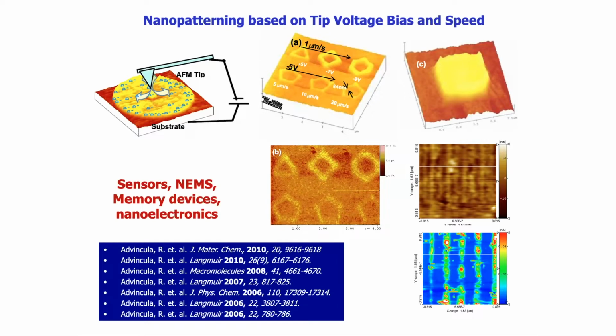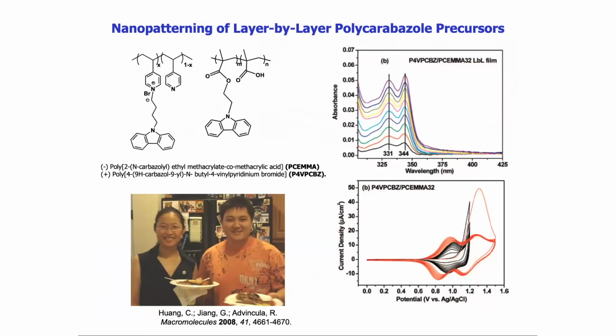Now, this strategy was employed in a number of demonstration devices where we can vary the voltage or current, we can vary the speed of writing, and therefore change the feature sizes of the nanopattern. These are basically 100 nanometer or less patterns, where we can also use lines, different geometric shapes, and actually use this to demonstrate a type of memory device that was patterned by the AFM.